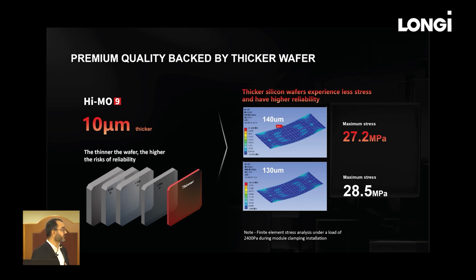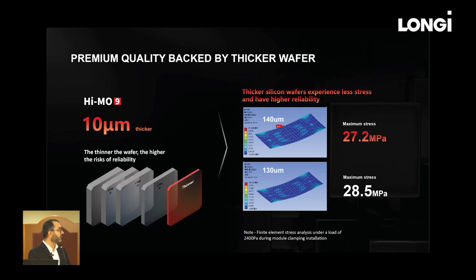With the price dropping, this is a very big issue, as some of the manufacturers have started to thin their wafer. But with Hi-MO 9, it actually has a thicker wafer than even the normal TOPCon. So it's about 10 micrometers thicker, so maximum stress is increased up to 28.5 megapascal.